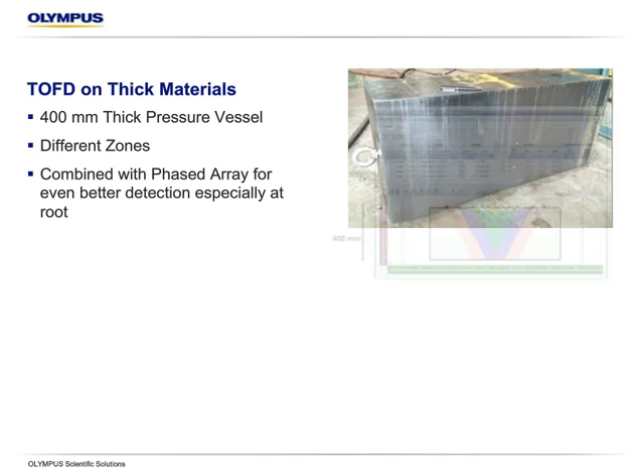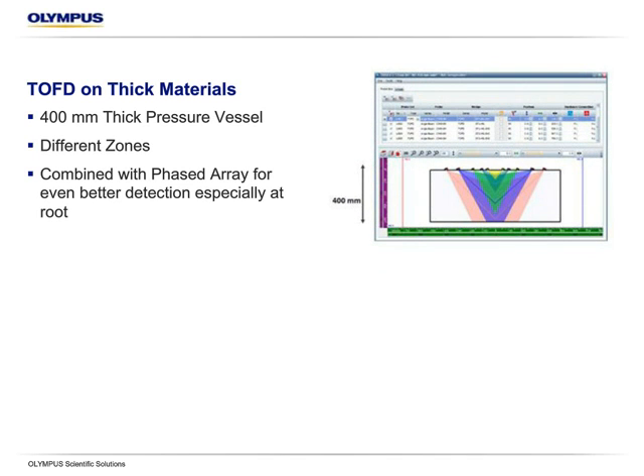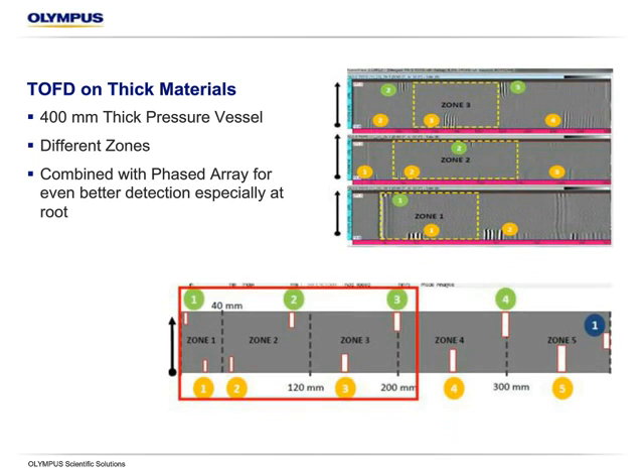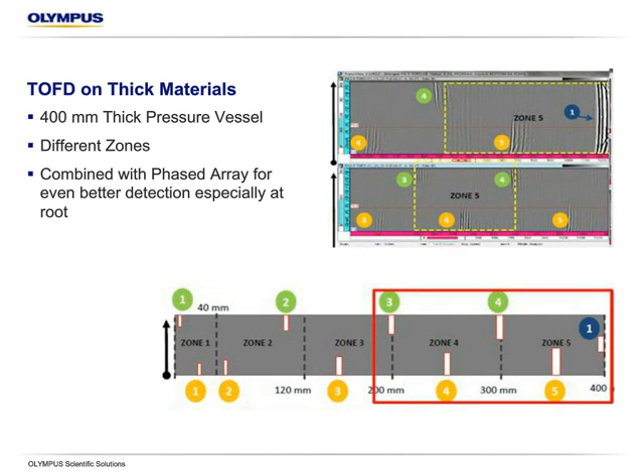So here's a schematic of how we set it up. So we had actually 5 pairs of TOFD in order to cover all at different focus zones. Here's the display. So we're able to detect all these defects quite well, actually. So you can see the different zones, different defects coming up in the TOFD. Obviously a little hard to see in the display here, but basically split it into zones, each pair responsible for a certain zone, which is typically what we do, so that we don't try to use a single TOFD pair for too big of a zone. We're going to lose resolution and sizing capability.